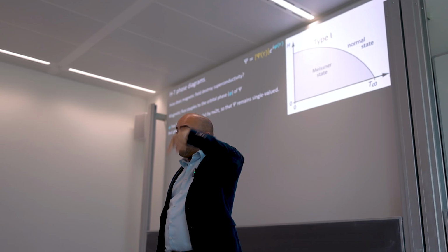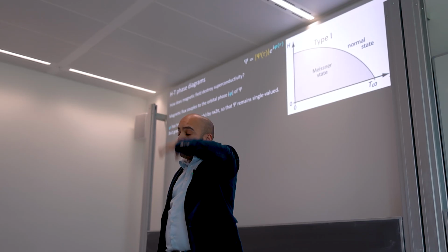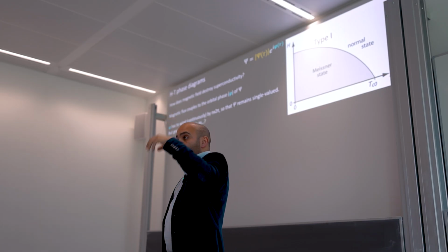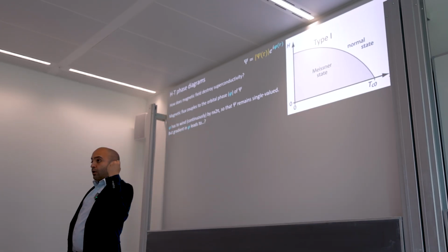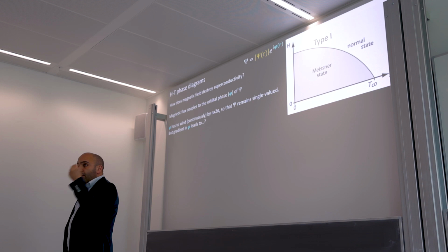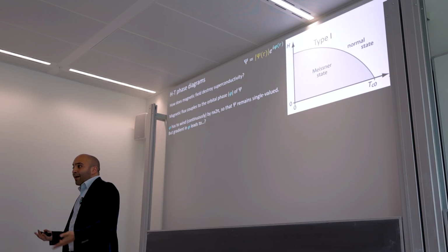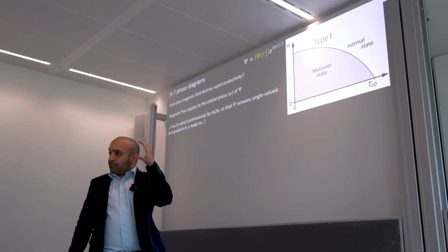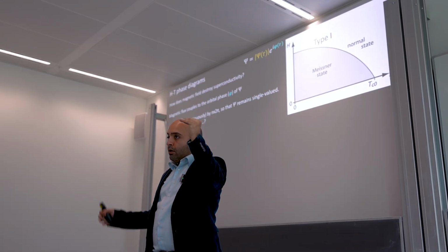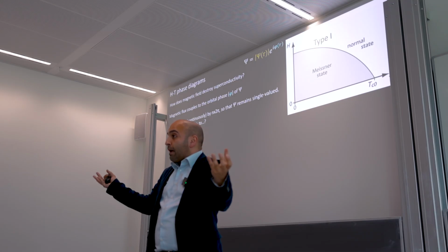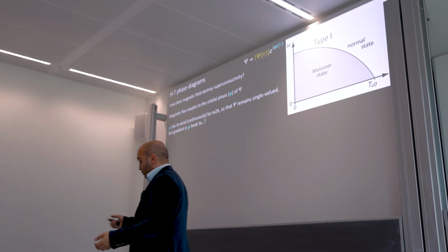When the supercurrent that you generate, the kinetic term as you said, reaches the energy of the gap, that's when you lose superconductivity. So you apply a magnetic field, it costs kinetic energy, even though it doesn't dissipate, because we're talking about actual charged particles going round. And that kinetic energy at some point gets too large, it becomes bigger than the size of your superconducting gap, the energy of your condensate, and you lose your superconductivity.